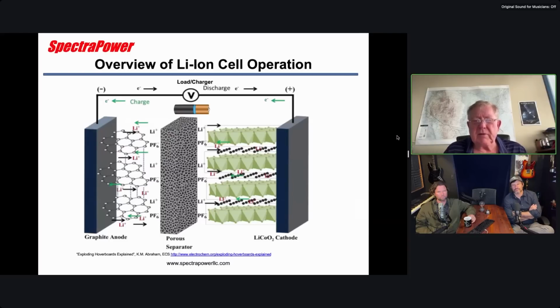Now, one of the most dangerous situations for a lithium-ion cell is overcharge. And the reason is that you're going to go up to about, typically for cobalt, 4.20 volts as your maximum charge voltage. But if you go over that, say you go up 5 or even 10 volts, you're going to pull all of these electrons out of the structure in this cathode. You're going to weaken the structure of the cathode. When that happens, it basically starts to dissociate. It's got oxygen in it, and so you've got oxygen and lithium, and the cell, if you keep overcharging, it will explode.